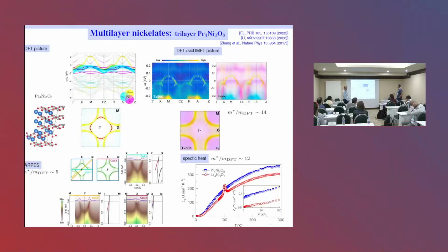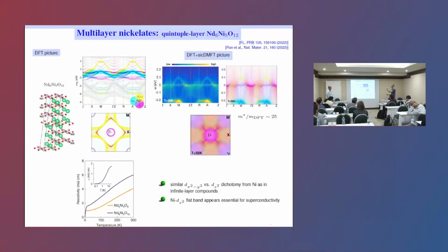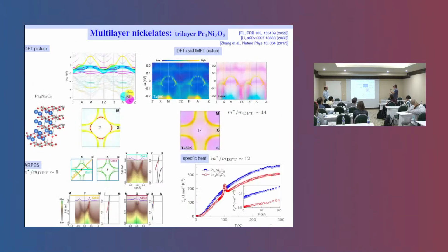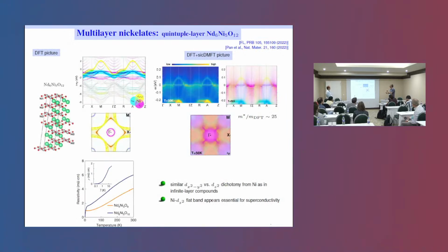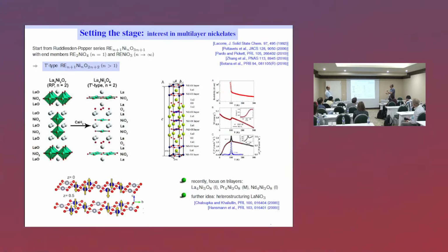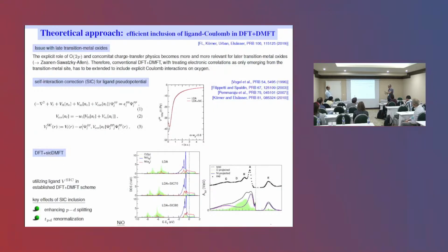For the 5-layer, as I said, the Kondo scale is very low, so I would not claim it's saturated at 30. I did a calculation at 30K, and it's not quite saturated. But even for the 3-layer compound, where it's already very high, it's more or less saturated. But it's very highly correlated, whereas the infinite layer, at stoichiometry, is in my case Mott insulating. So thanks for this question, which I didn't put very strongly to everyone's mind. I think these oxygen correlations bring a boost to the correlation. So in Karsten's calculations, they have a renormalization of 4 to 5, which is still good or strong, but not really super close to Mott criticality, whereas in my calculation you're close to Mott criticality for x2-y2.